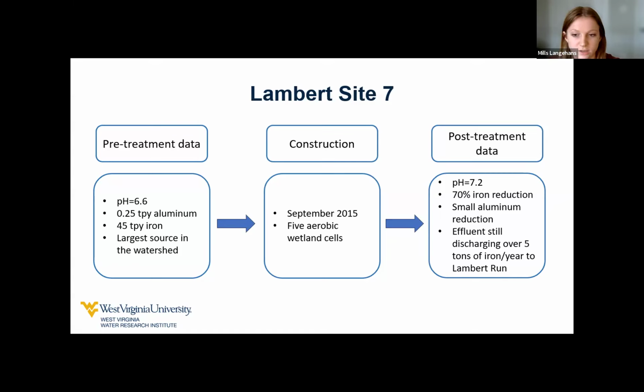Commonly, this exceeds 1,000 gallons per minute discharge. So back in September of 2015, a treatment system was constructed that consisted of 5 aerobic wetland cells. And upcoming, I'll have an aerial picture to show you of what that looks like. But after that was constructed, we see pH comes up a little bit more, closer to neutral. And this showed actually a 70% iron reduction and a slight aluminum reduction. But we found that it was still discharging over 5 tons per year of iron to Lambert Run. The goal is 0.